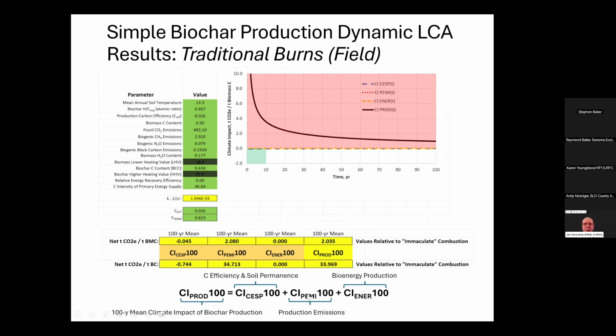So we focus on production emissions, which is the main thing we've been doing in this study, but we also kept track of carbon efficiency and estimated how long the biochar would last in the soil based on the temperature of the soil and the hydrogen to carbon organic atomic ratio. So the results over time are summarized in the upper right, where the overall climate impact of production is just this heavy black line. And you see it's well above 0. We're not carbon negative by any stretch of the imagination, but it comes down quickly. Most of this high value is due to the black carbon actually, that's the main issue, but other things obviously contribute.